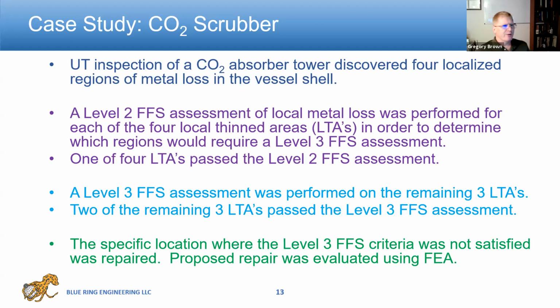What we did was we actually did a level 2 fitness for service assessment on each of these. This involves doing step-by-step calculations where you're computing kind of an average thickness and comparing that to how much thickness you need. Again, in the course, we'll go through that step-by-step. Turns out that one of those 4 areas actually passed the level 2 assessment. So that area was no longer a concern.